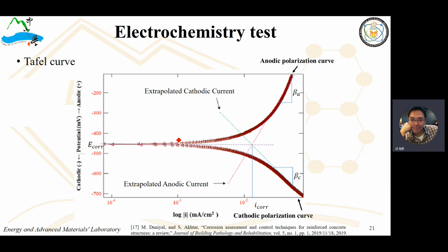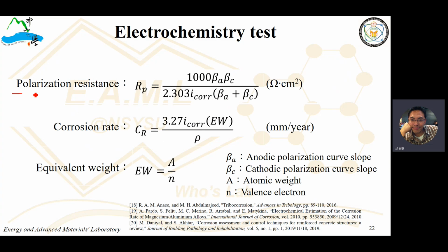And we can find out the Tafel curve. Okay, if we figure out the tangent of the anodic and the cathodic polarization curves, we get the intercept right here, okay? And then we can find its corrosion current and the corrosion potential. Of course, what we desire to get is... Sorry, that's wrong. I have to correct it. The higher corrosion potential is what we want, and the lower corrosion current is what I want, right? Okay, and then we can calculate its polarization resistance and corrosion rate by the equivalent weight.